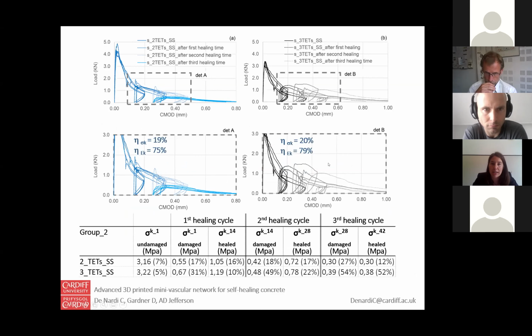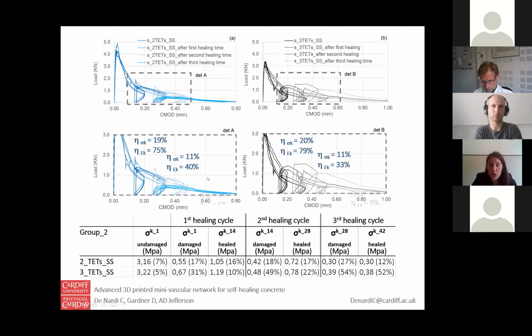After the first damage and healing cycle, in samples containing 2 TETs, we can see a healing recovery in terms of strength around 19% and then 20% in samples containing 3 TETs. And as concerns the stiffness, we have a healing of around 75% and 79%. After the second damage healing cycle, the trend is still positive. And in terms of strength, the recovery is around 11% in both cases. And considering just the stiffness, we are around 40% and 33%.